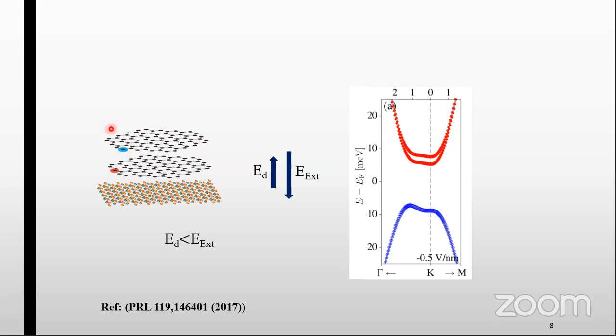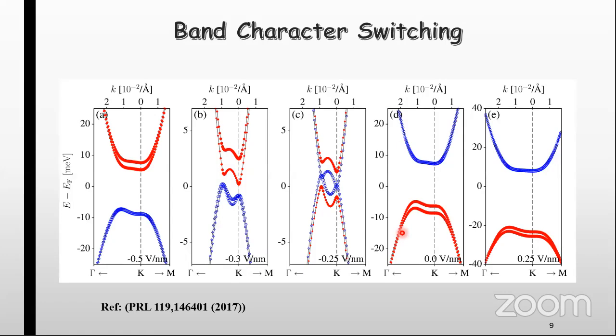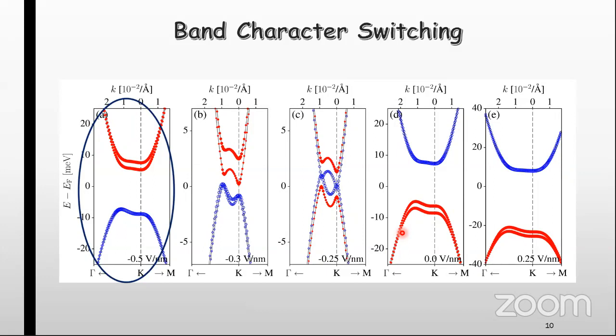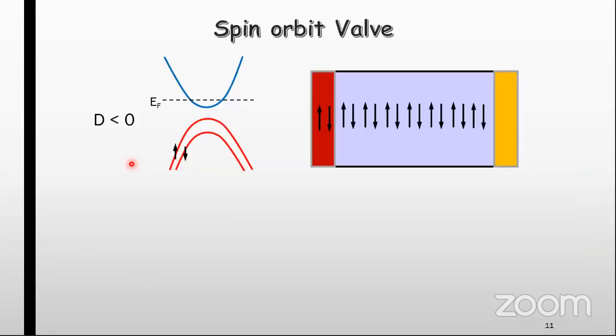And there will be a weaker spin orbit coupling in the top layer. So again, there will be negligible splitting in the valence band. So here we saw the band characteristic has switched. This is what we have shown. We started from here, and by applying an external electric field, we got this band structure where the splitting has changed from valence band to conduction band. So this is actually a very interesting problem.